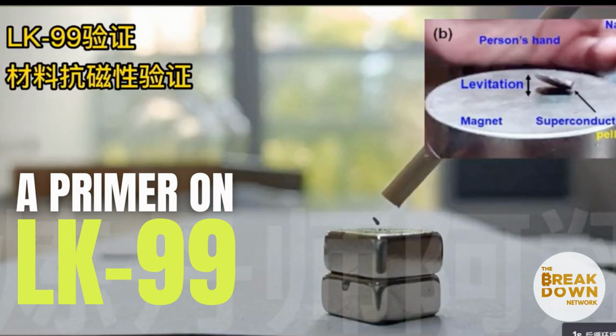This has a significant impact on the apatite crystal structure because copper is quite a bit smaller than lead. The researchers claim the overall volume of the sample drops by about half a percentage as well, and that change is accompanied by shifts in the orientation of various atoms and bonds. That means changes in where the electrons reside within the material. That change appears to be critical to the LK-99's behavior.